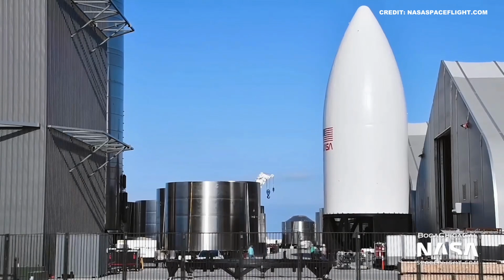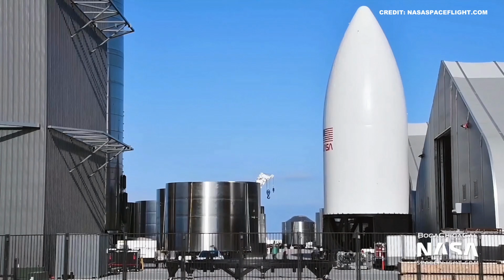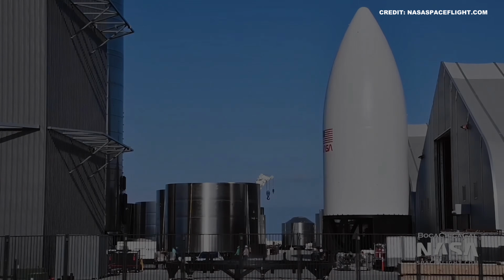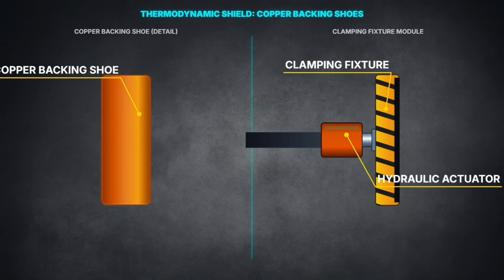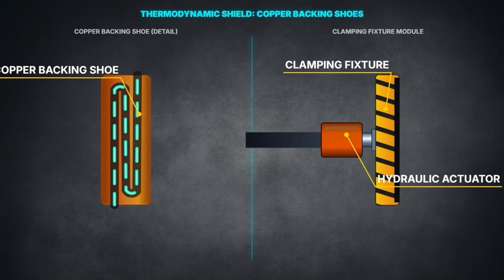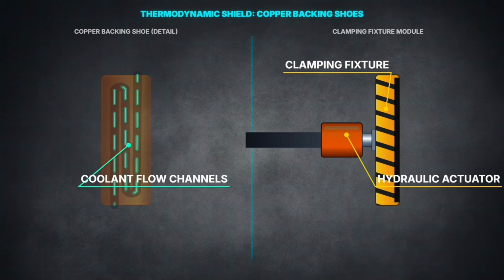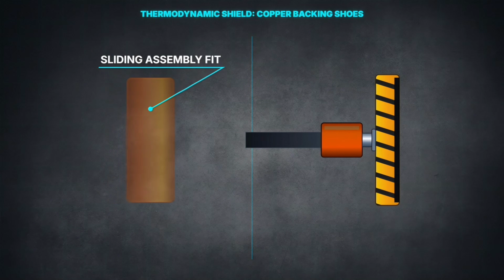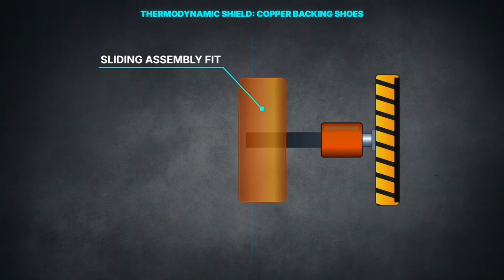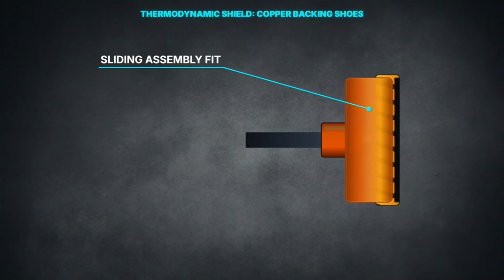To defeat this, the internal mandrel's equipped with copper backing shoes. These copper blocks press directly against the backside of the seam. Copper's thermal conductivity is 25 times higher than stainless steel. It acts as an instant heat sink, sucking thermal energy away from the joint interface. Water channels inside the copper shoes continuously circulate coolant, preventing the steel from ever reaching its buckling threshold.